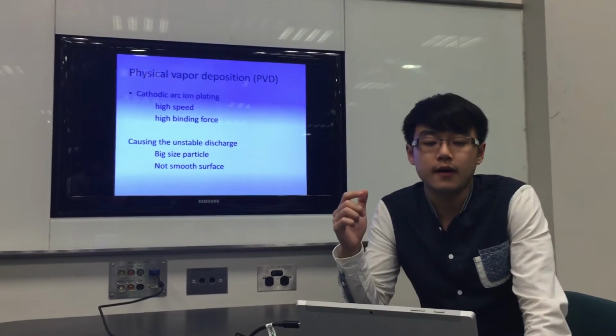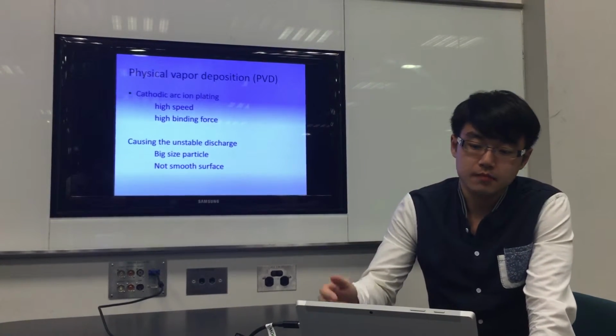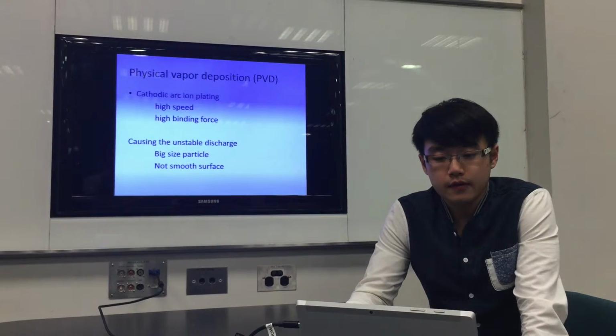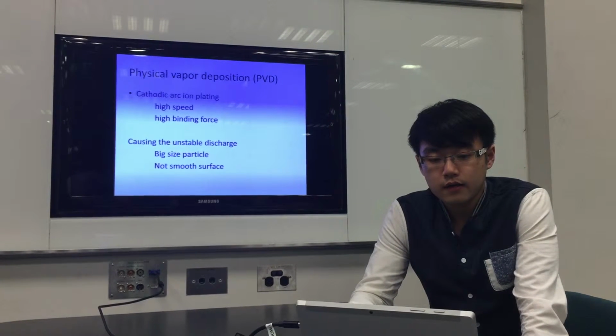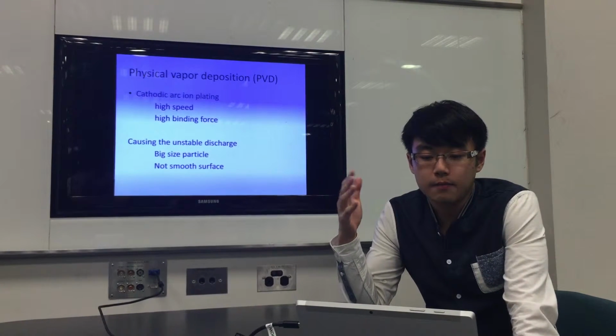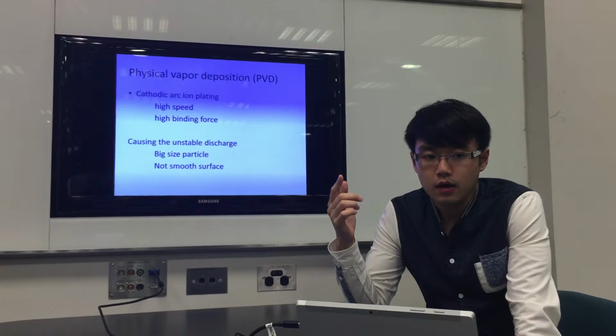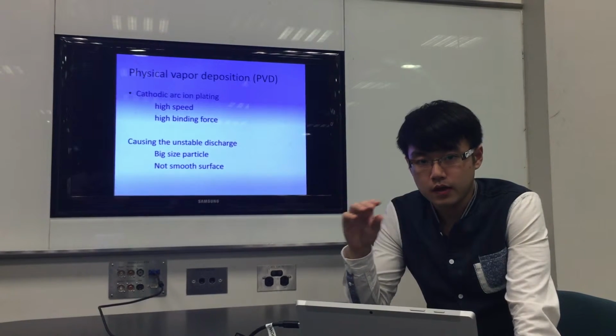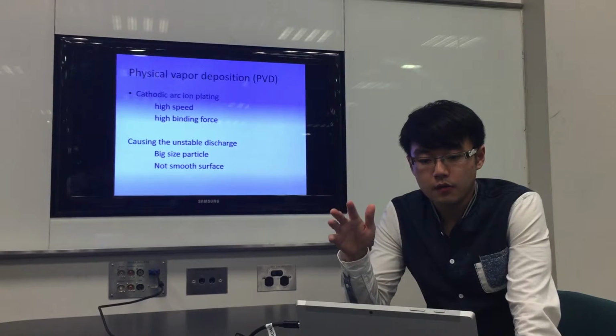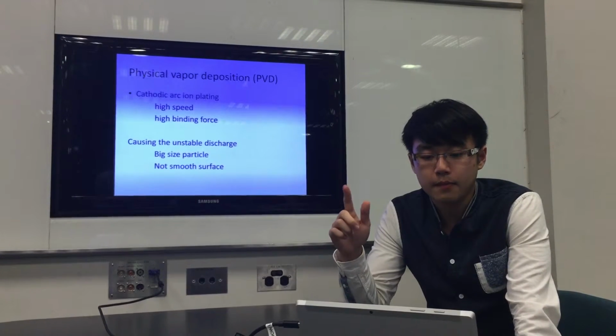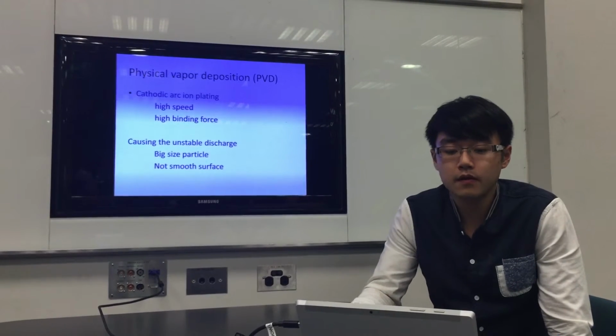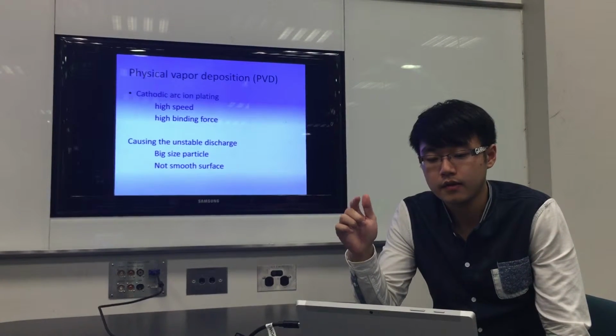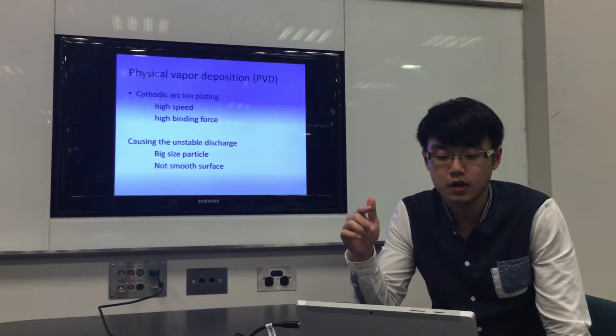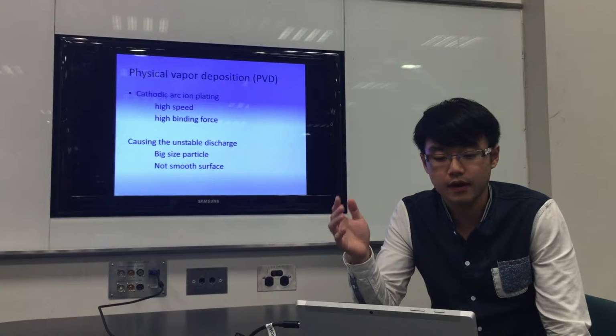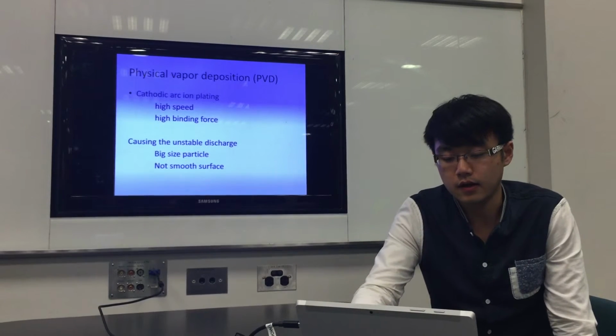Okay, the next method is physical vapor deposition. This method is what people always use. The first method is cathodic arc ion plating. In this method we use electricity to put the coating onto the metal, so it has high speed and high binding force. But because the voltage we use leads to unstable discharge, the particles will be big and the surface not smooth.